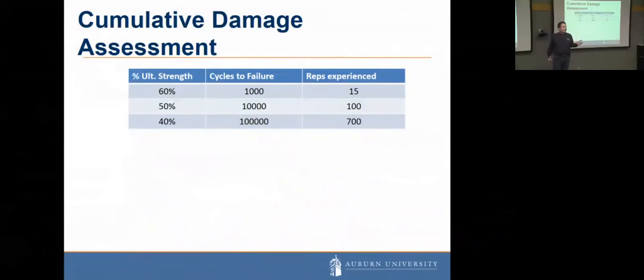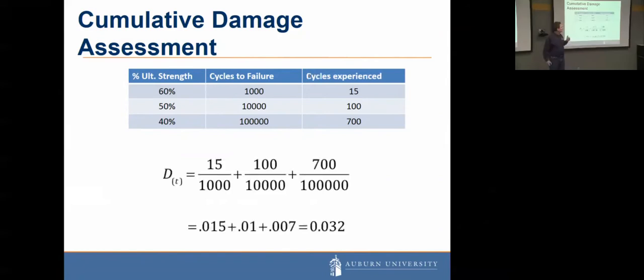But fatigue failure has a technique called the Palmgren-Miner rule, which will allow you to say, okay, at maybe 60% of your ultimate strength, you might be able to have 1,000 cycles to failure. Let's say you did 15 during a workday at that level, and you did 100 at 50% ultimate strength, where you could have 10,000 cycles till failure. And at the 40% level, you could do 100,000 cycles, and you did 700 cycles there.